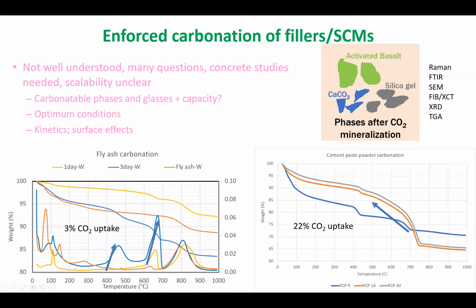Why don't we do this? Because this is really a synthetic system. Nobody does synthetic cement paste or recycled cement paste. But we kind of use this as our end case, where we really know that almost nothing we do, short of putting in a slurry of calcium hydroxide, will show these levels of uptake numbers, at least for cementitious materials. So this is pretty consistent with literature. There's a couple of studies on this, but this seems to be about the maximum that we can get. But for most realistic materials, it's actually 3 to 10%, right?